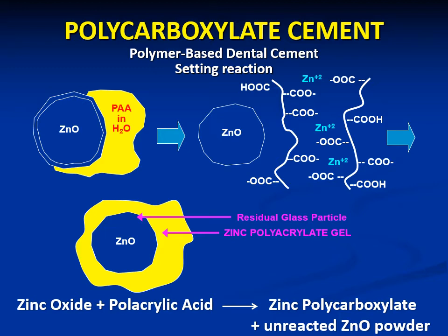Embedded in it is the residual unreacted zinc oxide powder. The gel matrix is a weak matrix, and also the polyacrylic acid can react with the calcium of the tooth structure the same way through the carboxyl group.